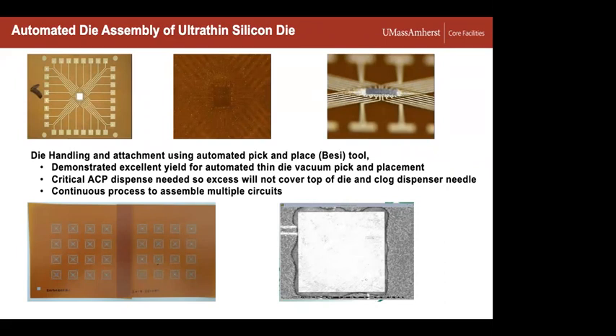The other advantage here is if you get thin enough, and that's believed to be around 30 microns, the actual silicon die becomes flexible. So as you bend this substrate, if you need some conformal type of application, you are not going to further stress that device and further impact or damage the conductive leads or the attachment. So that electrode interface could be critically impacted if this starts to bend.